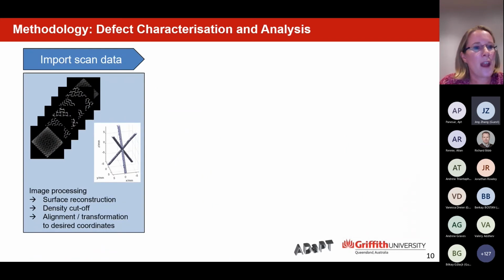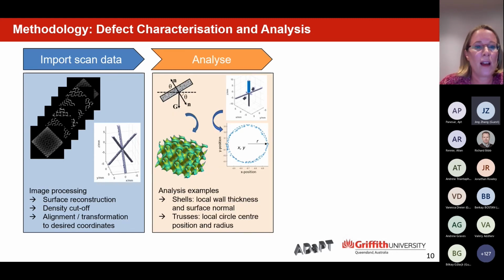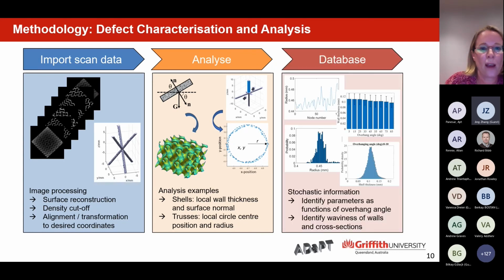In terms of methodology, how do we analyze this? So we're working a lot with X-ray data in terms of image processing, reconstructing the image, density cutoffs that also affect the porosity, and then alignment and transformation to the desired coordinates. We then perform analysis via scripting and automated manners in various codes, looking at local wall thickness and surface normals for the shells, looking for the trusses at the position of the circular cross-section, the variation in the center position, and also the radius variation. And that gives us a database. So that database gives us stochastic information. We can either map directly or in long-term planning to understand our equipment, our materials, our structures better.